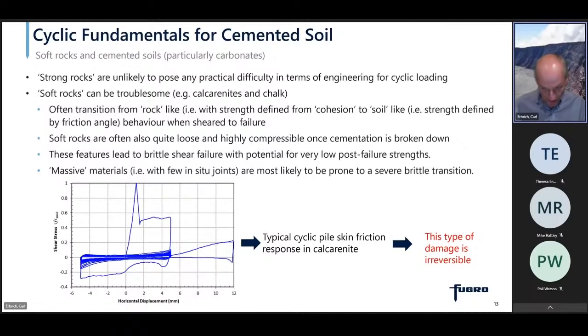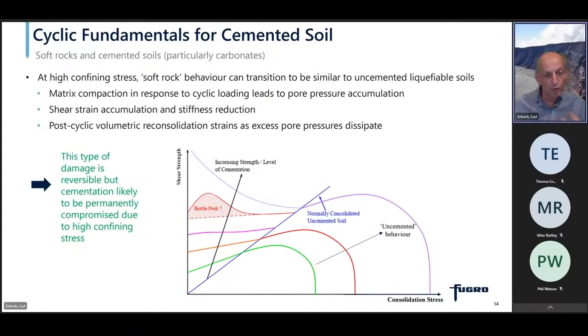And the important thing here, unlike the types of cyclic damage we were talking about earlier with the sands and clays, this is irreversible. Once this cementation is broken down, it's not coming back. It's gone for good. It's also worth remembering that because these materials are often quite compressible, at high confining stresses, the soft rock behavior can transition to be similar to uncemented liquefiable soils, where we're going to get matrix compaction.